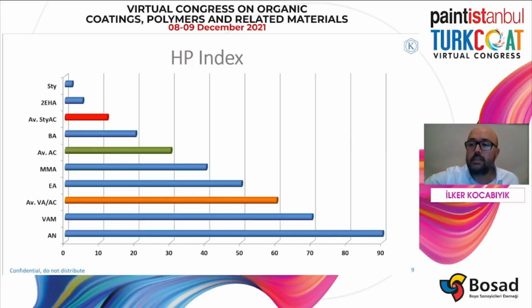As can be seen in this figure, where only main bulk monomers are shown, the middle of the scale is MMA, methyl methacrylate, with an HP index of approximately 40. And therefore, all other monomers fall under a category of hydrophobic if they are lower than MMA and HP below 40, or under a category of hydrophilic if they are more than MMA, which is HP above 40.